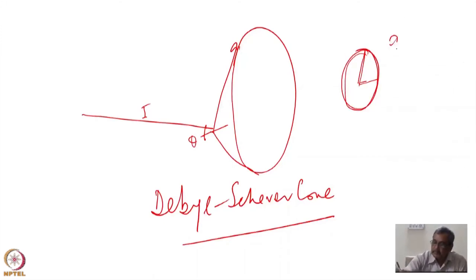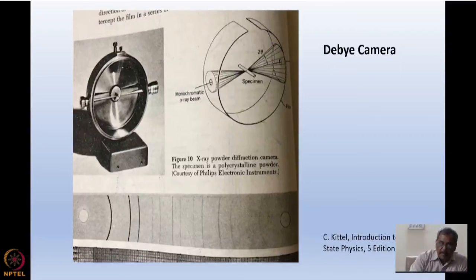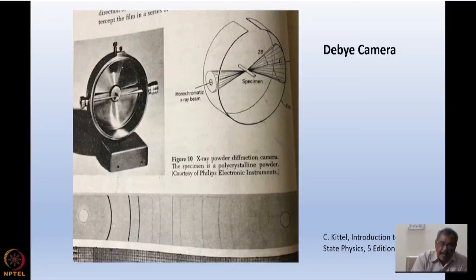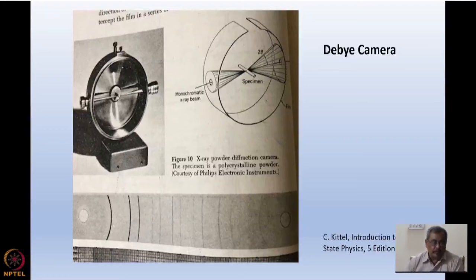So this experiment was done — and is done — to find out various d-spacings. You can see various d-spacings satisfying different angles because 2D sinθ = λ. In this case it was a monochromatic beam of copper Kα, so λ was 1.54 angstroms. In laboratory X-ray sources we usually use 1.54 angstroms. So λ is known, and knowing the radius of the rings around the incident point, we know θ, and from 2D sinθ = λ with known λ, we can find out the d-spacing.